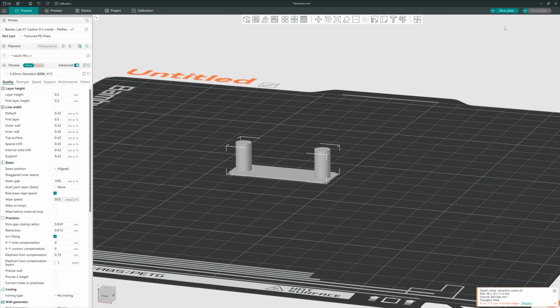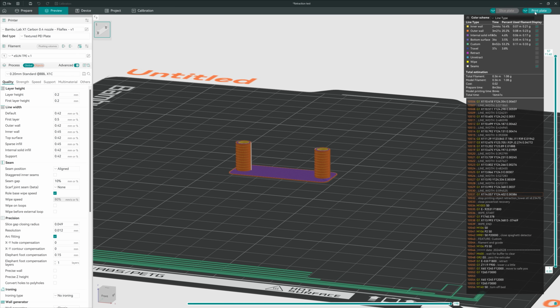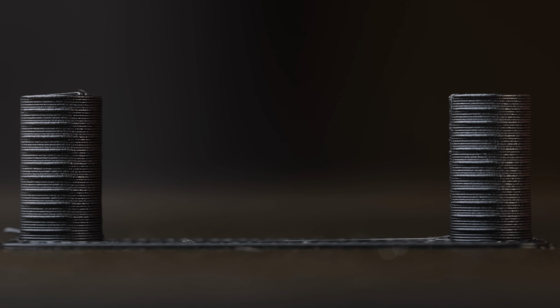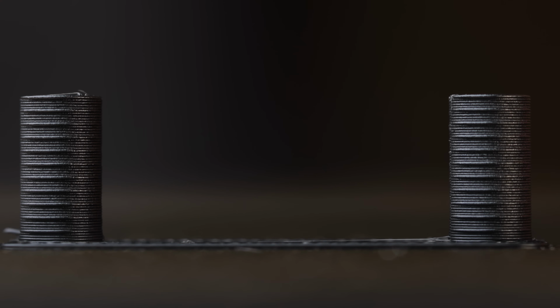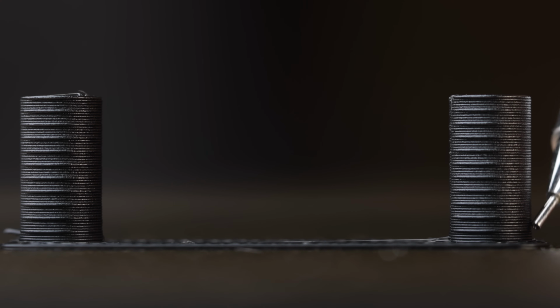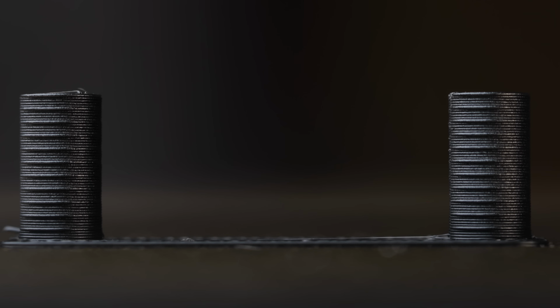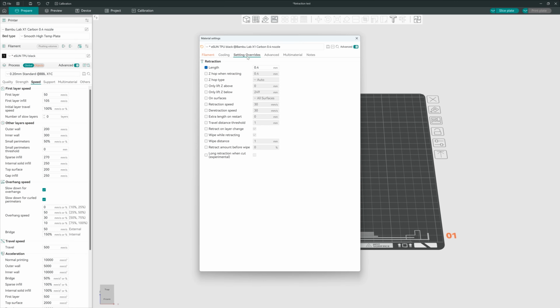Then I simply sliced the model and sent it to the printer. Here is the result. At the bottom we start with 0mm retraction. As we move up, each ring indicates increasing the retraction length by 0.1mm. Since there is no stringing at all, I will stick with the default value for generic TPU, which is 0.4mm.